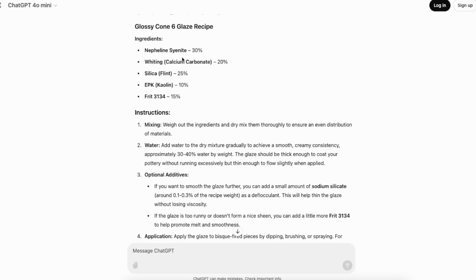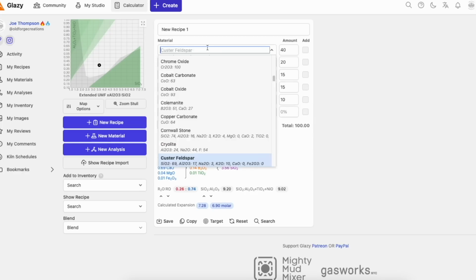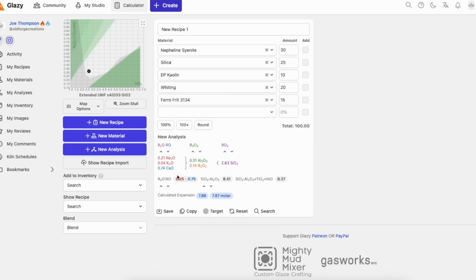I'd imagine if I stuck those numbers into Glaze, actually let's just do it. Those sensible flux ratio, possibly a bit less silica and alumina than you would like. The further it gets down into that corner, the more it crazes, and you've got silica on that axis, alumina on that axis, so you want to be kind of up there-ish. That's because it's got quite a lot of whiting, and you could quite easily drop that to 15 and add another 5 kaolin, and then you've got a more stable recipe. But you know what it gave us will be slightly more fluid, slightly more prone to crazing, but probably fine.